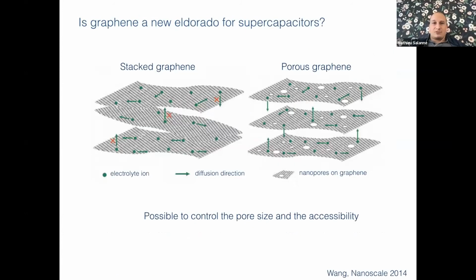Then more recently we switched to the study of supercapacitors, because when you think of it, we want a large surface area, we want carbon, we want confinement. So of course, people really quickly started to look at these systems. But of course, you cannot do this in normal graphene because you need to have diffusion inside the material. So the main experimental difficulty was to have some porous graphene, but this was quite overcome. But then a lot of the results were not as good as expected,